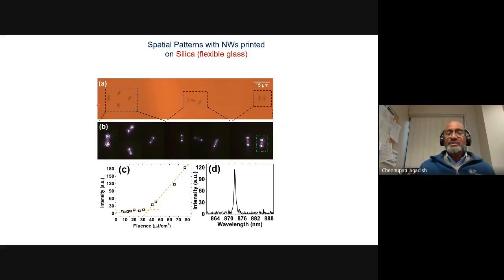You can see these nanowires on here in the optical microscope. And then you pump these ones and look at the light emission. You can see that the light is coming from both ends of the nanowire. And then also you can see threshold-like behavior, very sharp light emission, indicating that you can really get this transfer process, a gentle process.